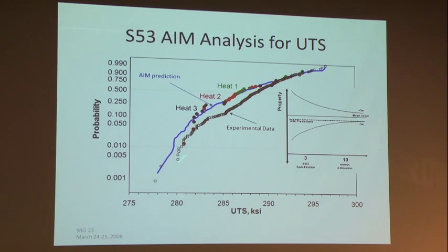This shows the predictions that were made. The blue curve is the Monte Carlo simulation of the shape of the function. This is the calibration of the first 3 heats. This then is the final validation where we meet all the requirements of the 10 heats. And once again, we got that 1% probability value within 1 KSI.